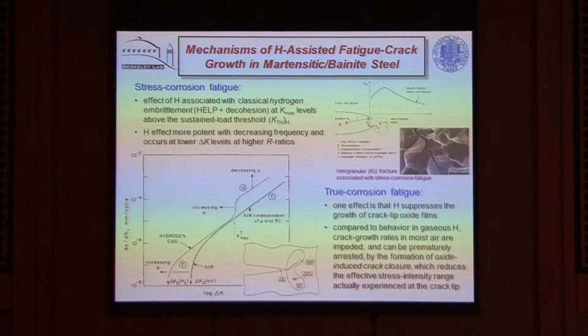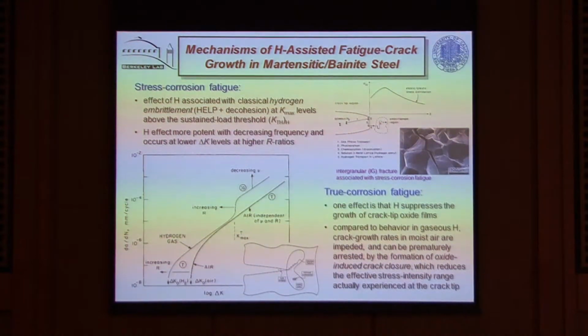Now, the complexity here gets very large, and one of the effects that we deal with down here is that not so much that hydrogen accelerates crack growth, but air can decelerate crack growth. In a moist environment, you form oxides at the crack tip. And at these very low growth rates, the opening of the crack, the so-called crack opening displacement, can be fairly small. And these oxides then can wedge the crack. The analogy is if you're talking and I put a donut in your mouth, you're less able to open and close your mouth. Doesn't seem very scientific, admittedly, but it's a very potent mechanism which basically reduces the growth of cracks at these low levels. So the complexity of mechanism here is important.